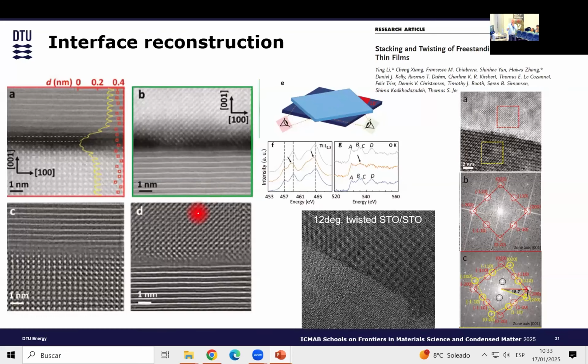When we saw this the first time, you could say, okay, you have a bond in one place and a gap in another place, so it's not really bound to each other. We think that it is bound to each other at this point, both from the reconstruction that we've seen and from doing an analysis across the different layers. But the question is why the contrast is there, because otherwise you would see something completely homogeneous all over.